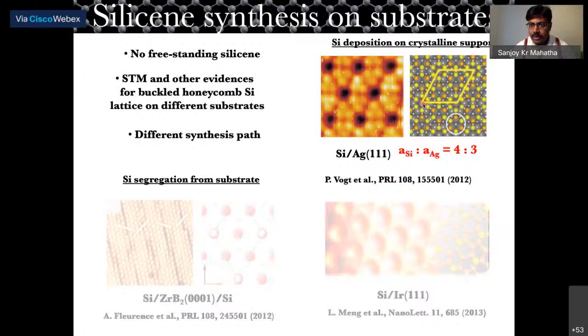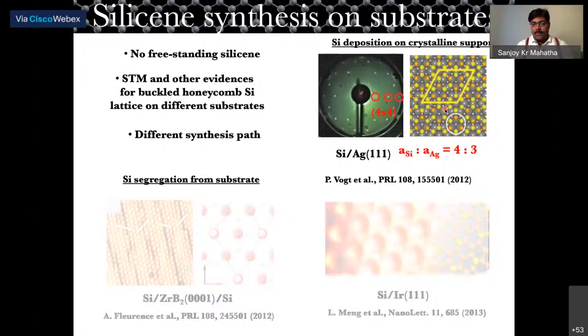So if you follow this, from here to here, you can see there are four silver atoms in gray: 1, 2, 3, 4. But along this direction, if you count the silicon atoms, there will be only 3. This is the reason it will give you a 3 by 3 or 4 by 4 structure of silicene, depending on what your reference structure is. And in the LEED pattern, because of this 4:3 lattice ratio, you would expect to see this kind of spots, which are called 4 by 4 spots with respect to silver 111. By seeing this spot, one would be able to understand if we have the right phase of silicene or not.